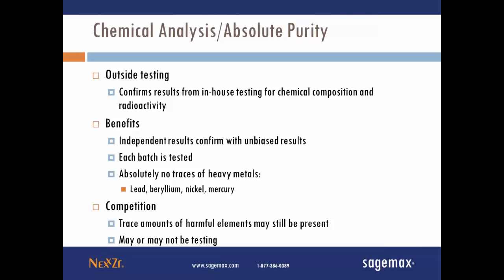So as Dan mentioned, we do also outsource some of our testing to independent labs to test for the chemical composition and the radioactivity. Radioactivity is not something that we can perform here at our facility. But the chemical composition, actually, we outsource too. We're very confident in our results of the in-house lab tests, but we do this to ensure absolute safety of our material. As I mentioned, it is an unbiased lab.